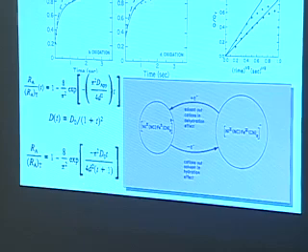So a given cation, depending when it leaves the surface, and this is where what you were saying comes in, samples a different environment. That is, if a cation leaving early on has this big open lattice, say, and it has a certain effective viscosity, if you will, for the cation moving through that lattice, and it sees a certain diffusion coefficient for the cation now. And that diffusion coefficient for the cation is coupled to the diffusion coefficient for the electron, because I can't do one without the other.